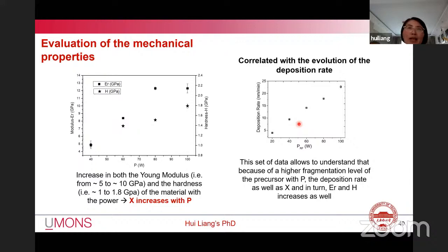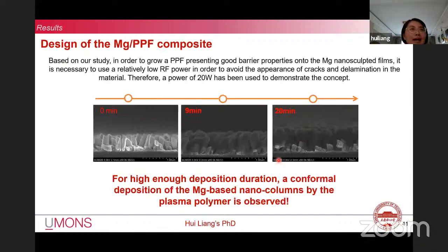More free radicals are produced during the collision process, and the deposition rate of the coating increases. This slide allows us to understand that, because of a higher fragmentation level of the precursor with RF power, the deposition rate as well as cross-linking, hardness, and Young's modulus increase as well. The design of the Mg plasma polymer film composite.